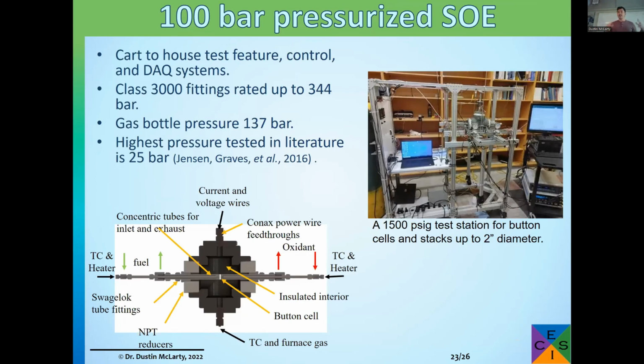We've been testing in a 10 bar facility that we developed years ago for testing commercial apparatuses up to 3 or 4 kilowatts. So it's a large 12-inch internal diameter that we can work in. But we really wanted to explore this at much higher pressure. So over the past 6 months, we've really built this first of its kind. We're not aware of anything that exists in the world that's like this, but it gives us the ability to test button cells and small stacks up to 2 inches diameter at up to 100 atmospheres.